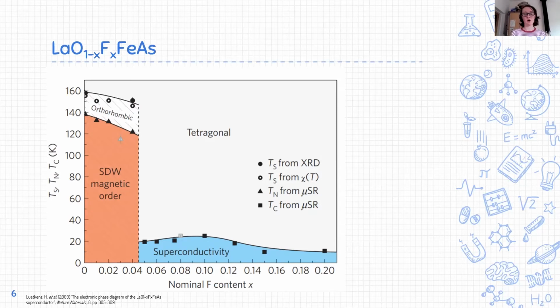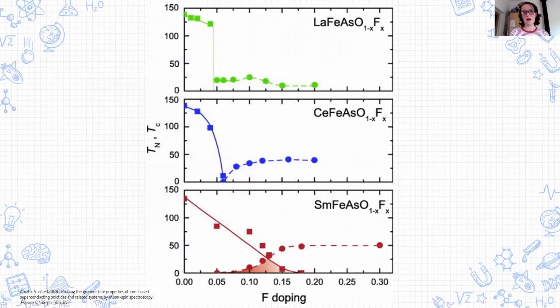So this generated a lot of interest, and there was a sudden flurry of research into this area. And other superconductors were found, but one of the first things that was noticed is that the phase diagrams for these different superconductors were looking remarkably different based on how similar the materials are. So here are 3 of them. And for all of these materials, the structure is the same and the composition is almost exactly the same. It's just the rare earth element that differs. But you can see just by looking at them, the phase diagrams look completely different. And this alone is quite odd.